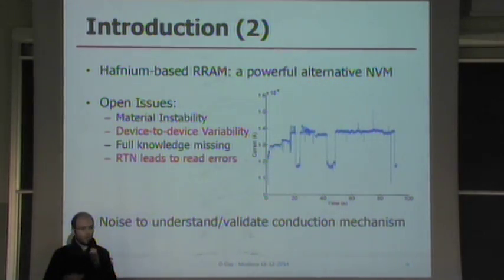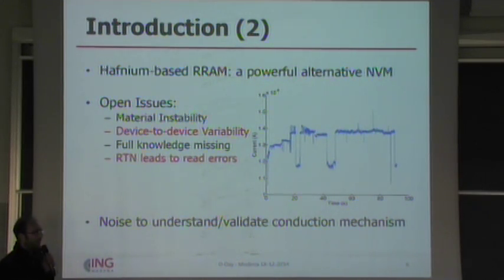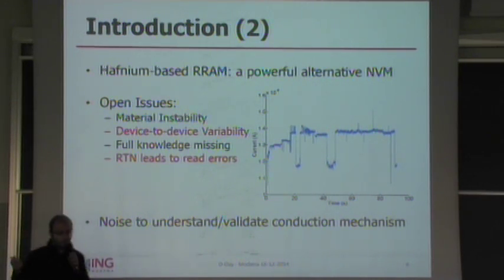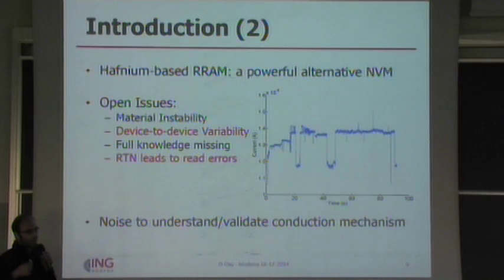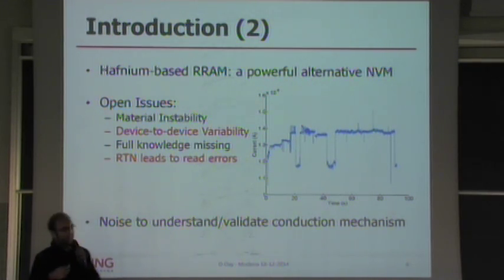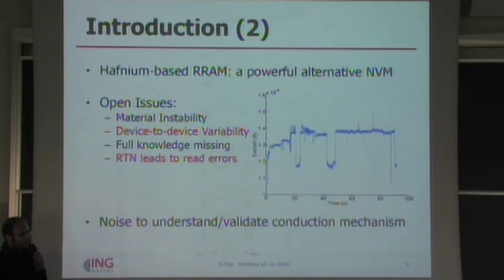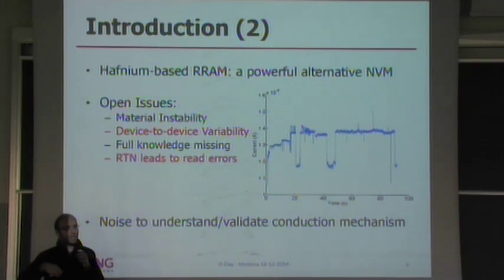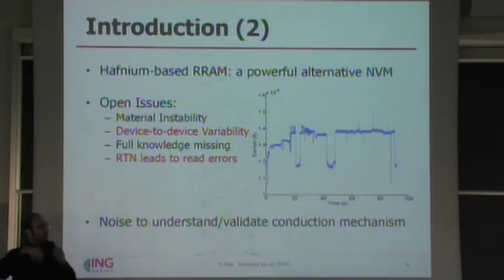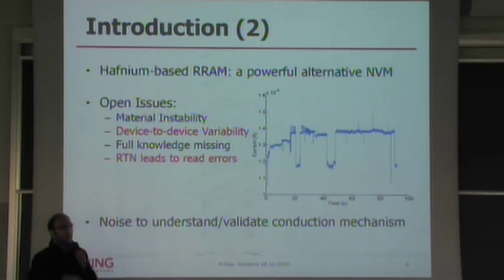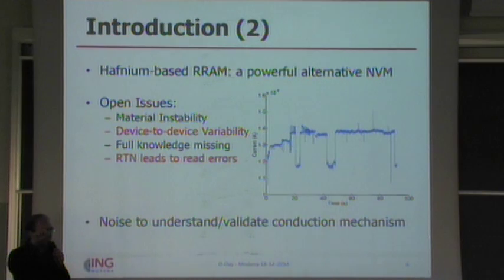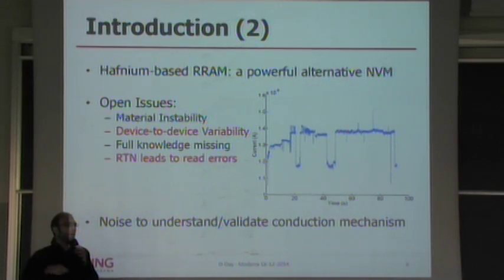But of course, it's not only wine and roses. We also have some open issues, most importantly variability issues, as I told you. The variability and reliability related issues are major concerns for this technology. The device-to-device variability can be quite significant, so different devices are going to behave differently, but also cycling variability. So the same single device from time to time is going to behave differently, which is a writing procedure related source of variability. But also, regardless of the particular resistive state in which we are at a given instant of time, we also have a read disturb.